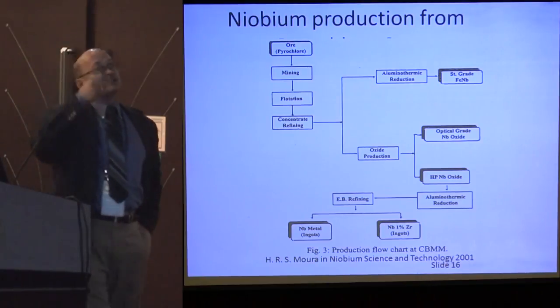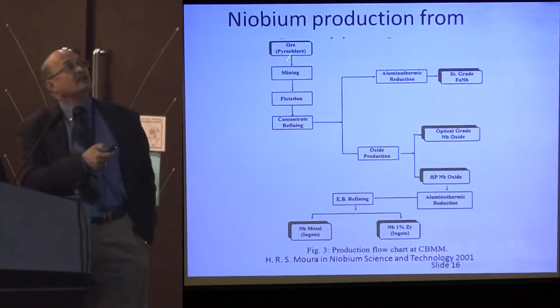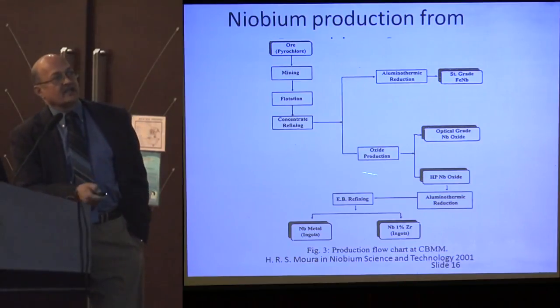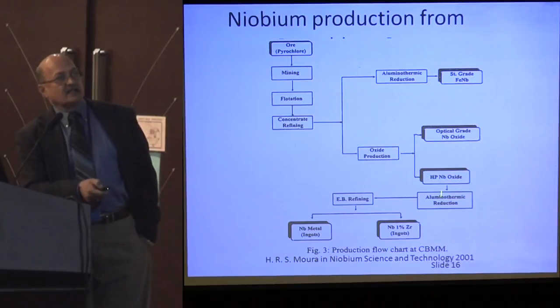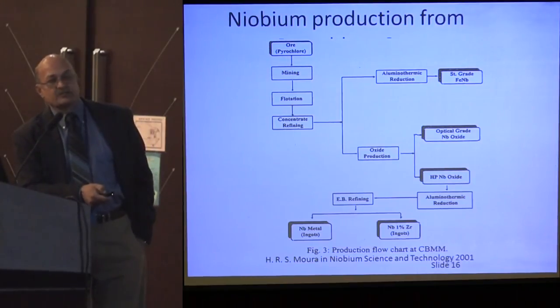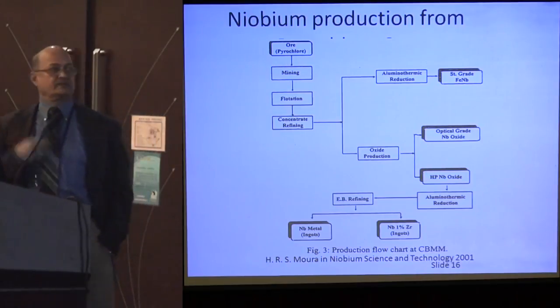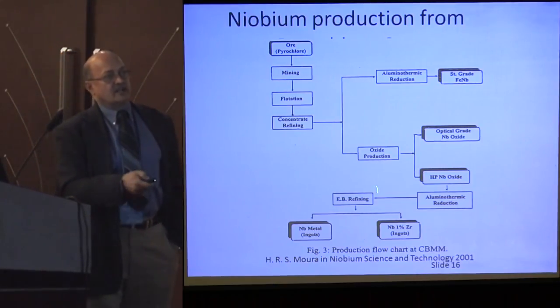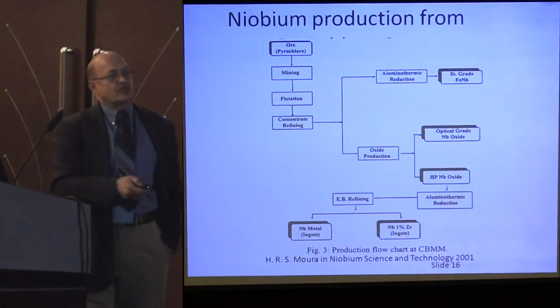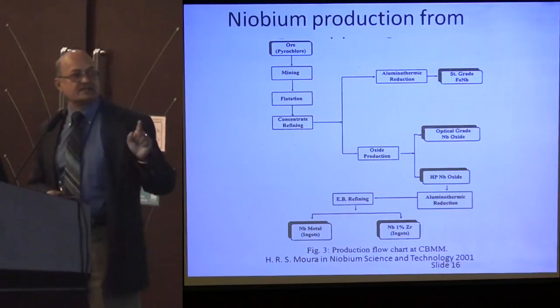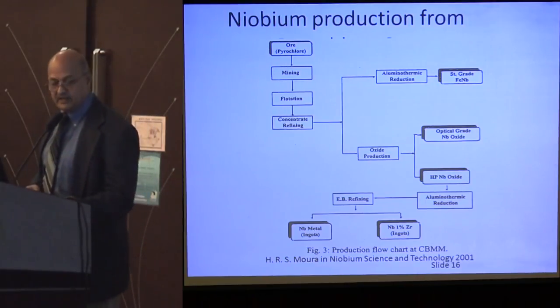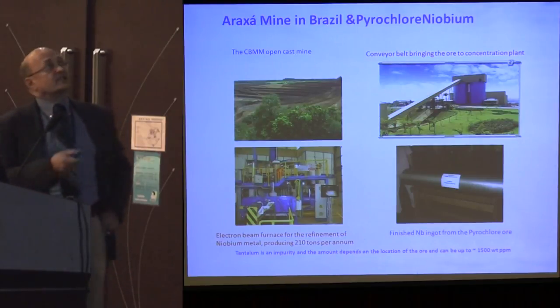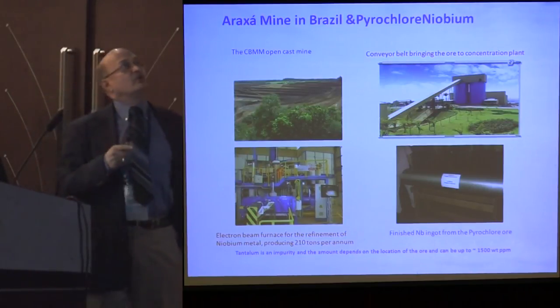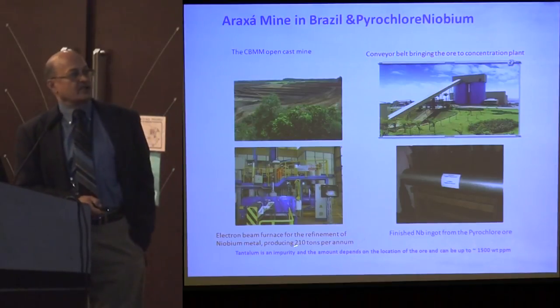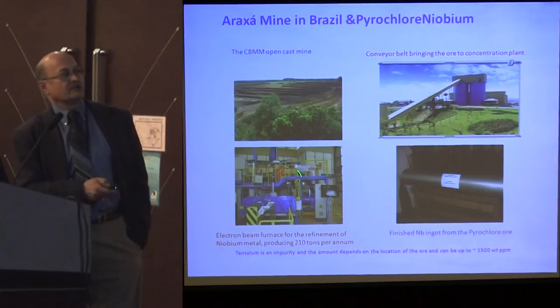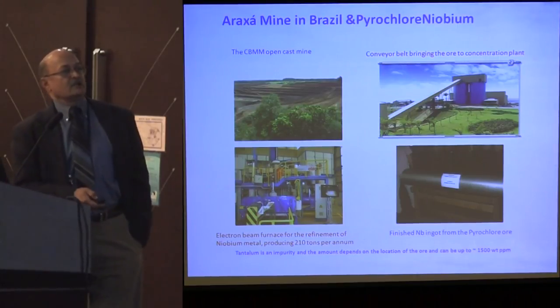This is niobium production from pyrochlore ore. This is the process here, and basically after aluminothermic reduction, you get the E-beam refined niobium ingots, which are taken by the vendor to produce niobium sheets. Whereas you can actually use the ingot niobium that's coming directly from this production, which may be less expensive, but the only problem is the tantalum content may be higher than the specs that are currently proposed or used. This is the largest pyrochlore niobium ore in the world, and they have a production capacity of 210 tons per annum currently for the finished pure ingot niobium, and they are planning to double this.